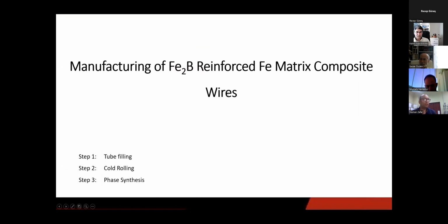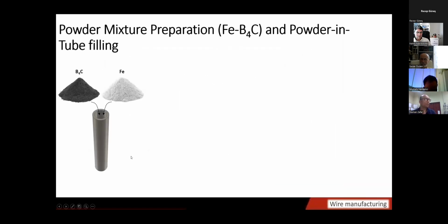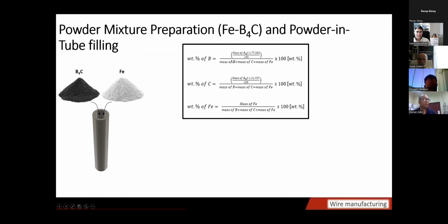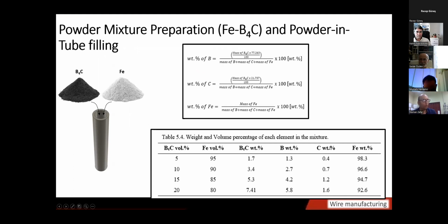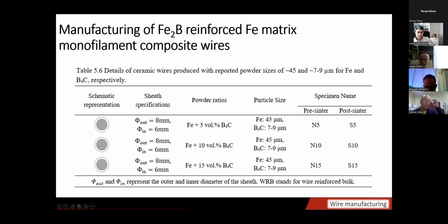The manufacturing of Fe2B reinforced composite wires is very simple: tube filling, cold rolling, and phase synthesis in a nutshell. Here is a schematic of tube filling. And this table is going to be very useful when we investigate the phase interactions of these materials at elevated temperature. Out of these powder mixtures, I have used these formulas to calculate the elemental composition with the weight percentage for these powder mixture ratios. These are the type of wires I have manufactured: outer diameter 8 millimeter, inner diameter 6 millimeter, with 5, 10, and 15 volume percent reinforcement of B4C particles. And these are the pre-sinter and post-sinter state wires.